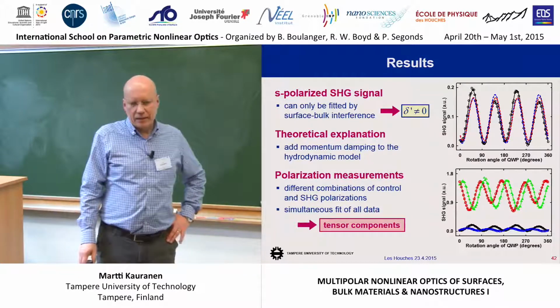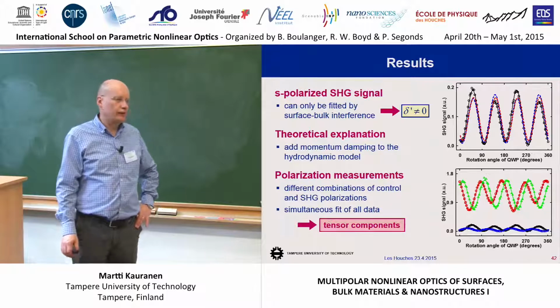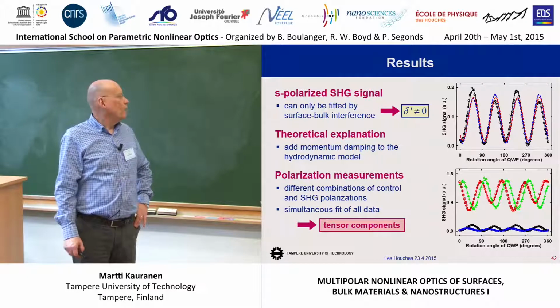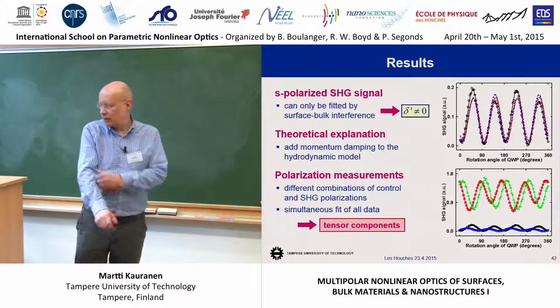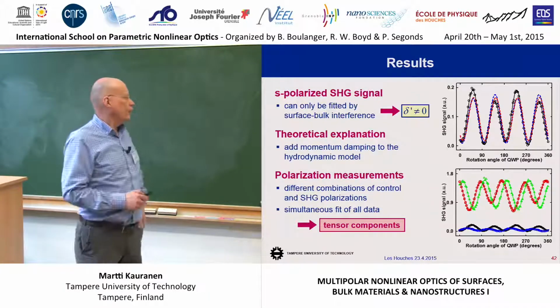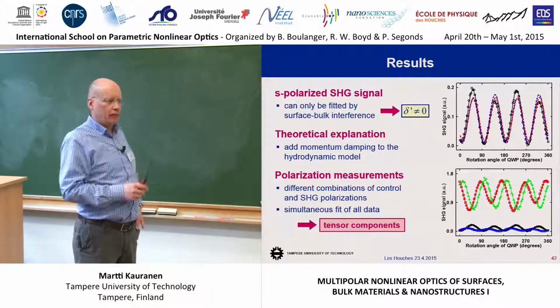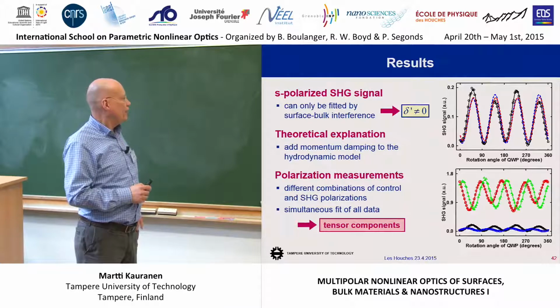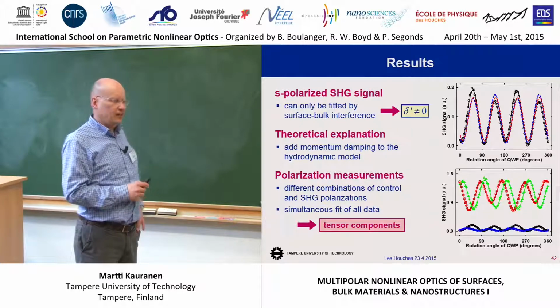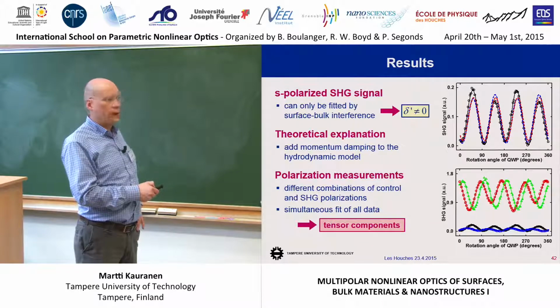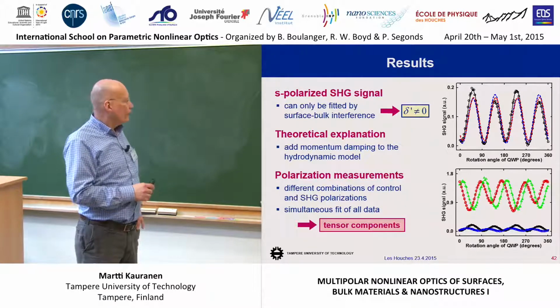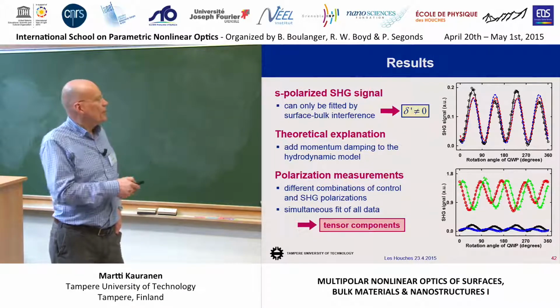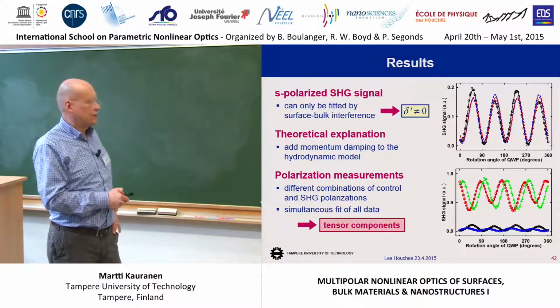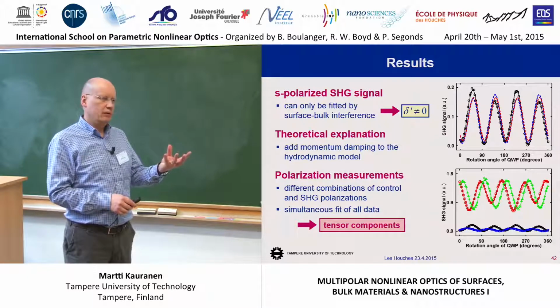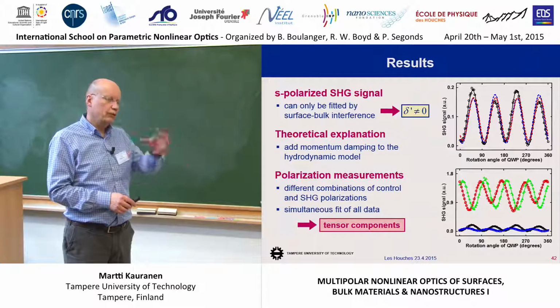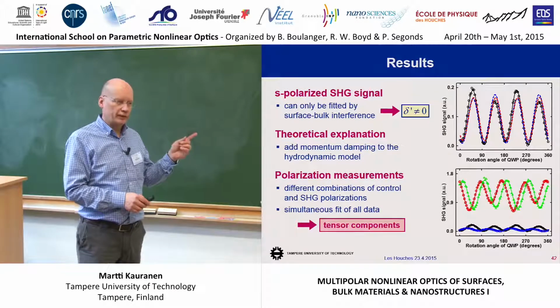But remember, I just said that these free electron theories say that there should be no delta prime for metals. But this problem was solved by a collaboration with John Sipe. So he modified these free electron theories by adding damping of the electrons. And then once you add damping into the hydrodynamic model, delta prime becomes non-vanishing. And furthermore, we then went on, because John Sipe provided us numerical results for these various parameters. You can use the free electron theory also to predict the surface responses.